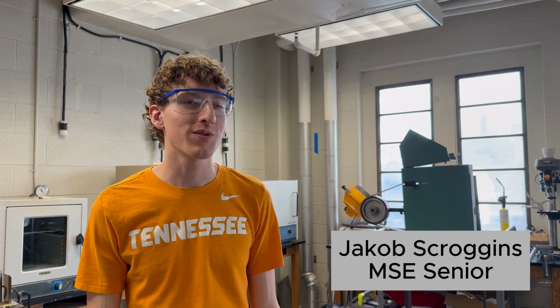With a fully optimized mold design, we partnered with Matthews Additive Technologies to print the mold. We selected the binder jet printing technique because it offers the ability to print complex designs at low cost. It's also simpler than investment casting. Casting was done at Andritz Metals. The mold was preheated and the steel was poured at 3,000 degrees Fahrenheit.